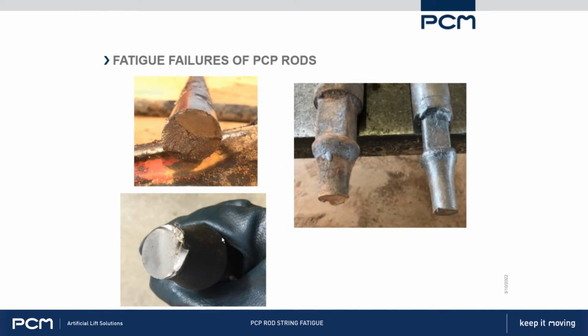The location of a fatigue failure is shown on these other pictures too. You can see the upset is right here. This isn't some kind of narrowing due to tension. This is the shape of the rod at the upset. We have the wrench flats. We've got what's called the bead, and then there's a transition down to the rod diameter. And in these two examples, the rod has failed right at the end of that transition, where the rod has reached its nominal diameter.